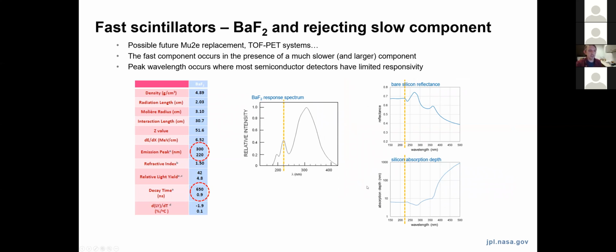There's sort of no such thing as a short pass filter which operates in the far UV because of that problem that I mentioned a few slides ago of a limited number of materials to choose from. And there's really not a material, for example, that absorbs low energy photons more than it absorbs high energy photons. Just doesn't work that way. So if you do buy ultraviolet bandpass filters that can operate, say, at Lyman alpha, you'll typically get a filter with a peak efficiency in the range of 10 to 20%.